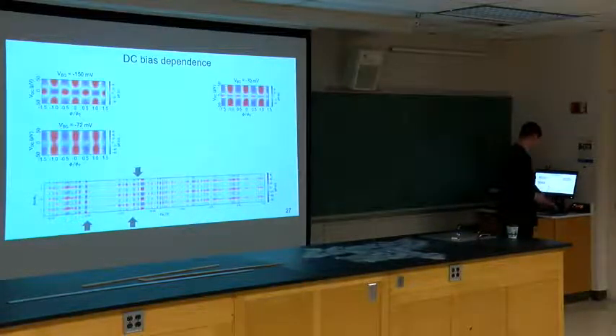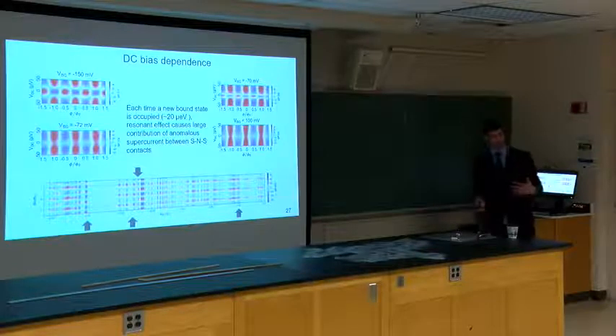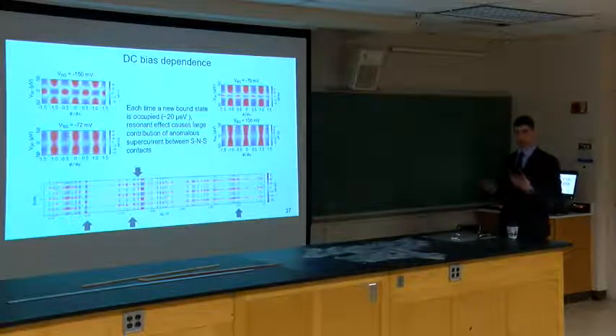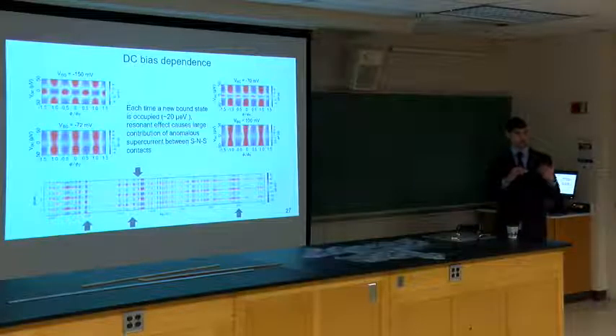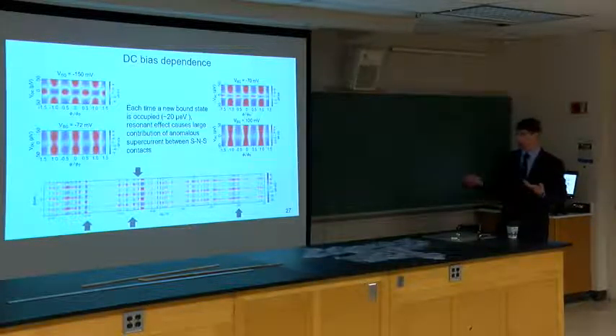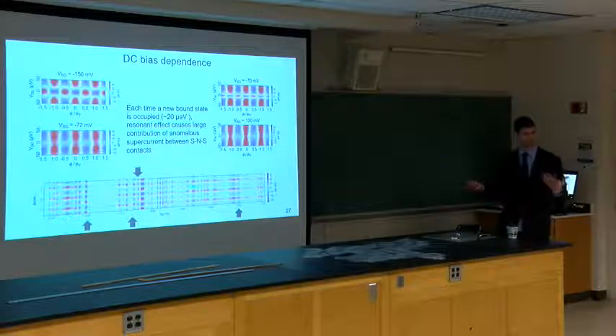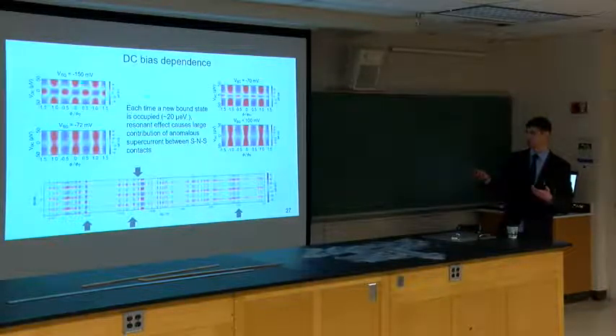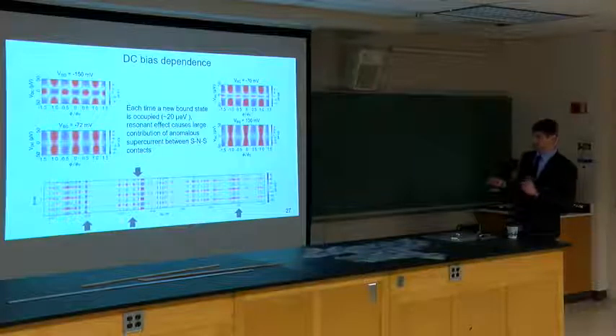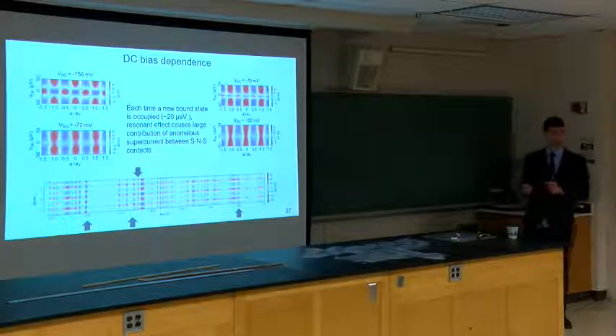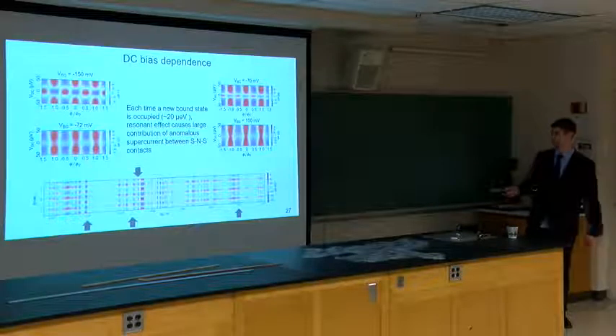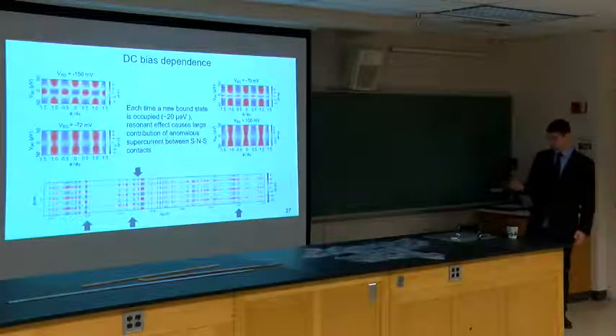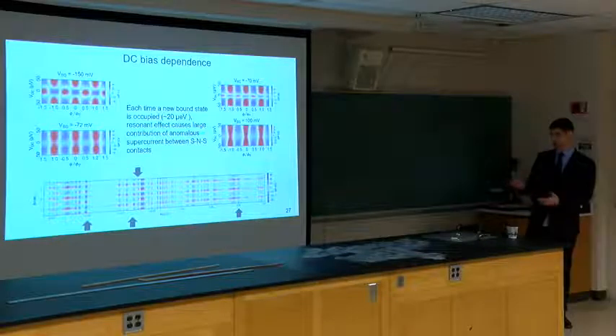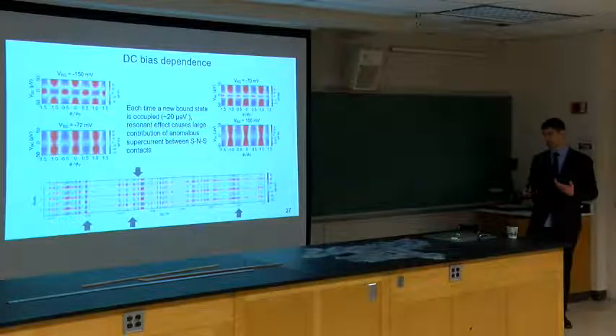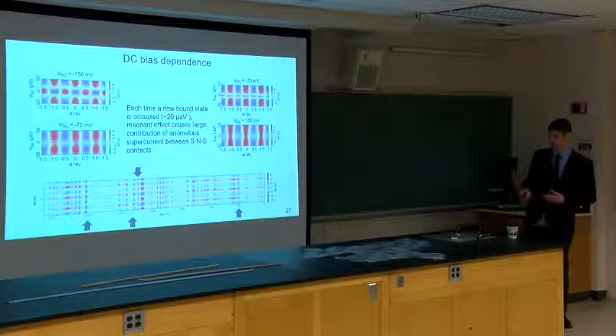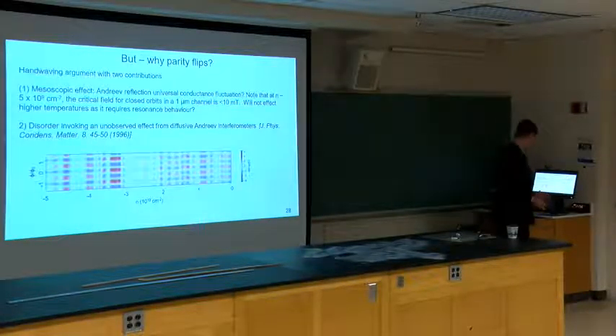So DC bias dependence, which is the bias dependence across the junction, you would think that as you increase the DC bias, you're going to effectively couple to a different bound state in the channel. And roughly, hand waving, it kind of does match. You can see the scale here. It's roughly about 20 microelectron volts. It does not seem to be consistent among gate voltages, though, which I don't have an explanation for, actually. I would love to be able to tell you something, but every time a new bound state is occupied, you start seeing either a rise or a drop in the resistivity. Now, why parity flips?